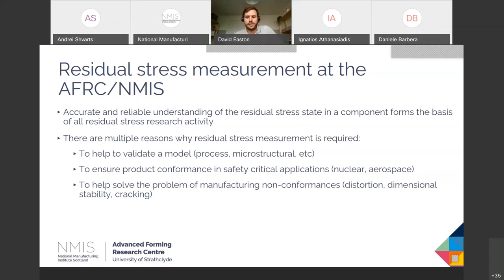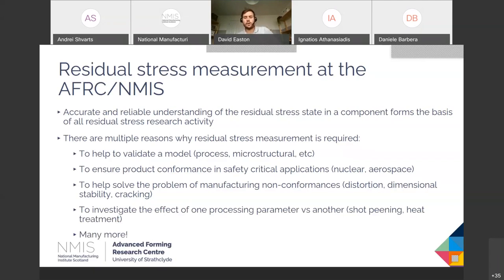A manufacturing company is having a problem with a part that's distorting, or a part that's cracking, or it's moving about once it's in service. So residual stress is an obvious candidate, and we'll turn to measurement. Or it could be to actually evaluate how effective one manufacturing parameter is versus another. Could be shot peening or heat treatment processes, or it could just be forming and forging processes. How do these affect residual stress? And we can design that process by measuring the stresses themselves.